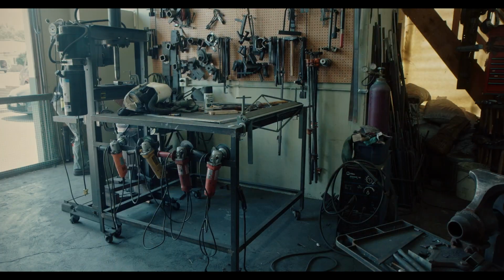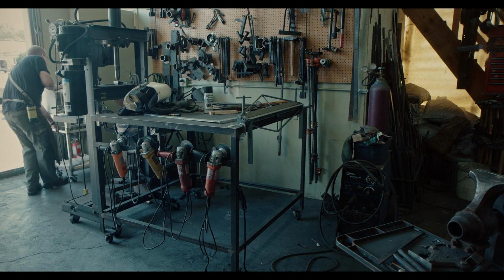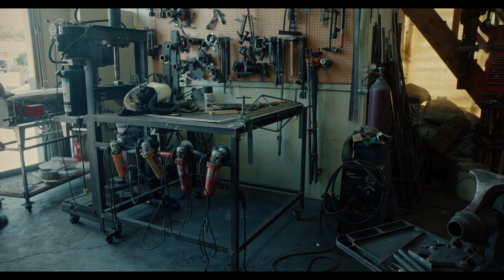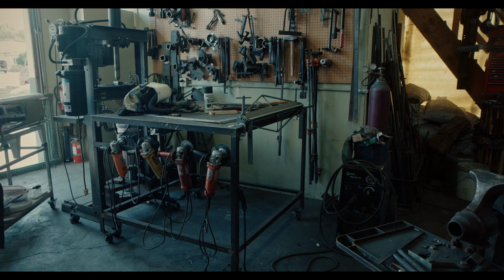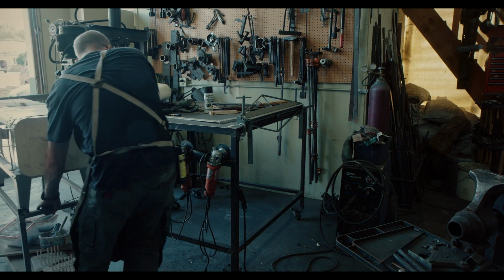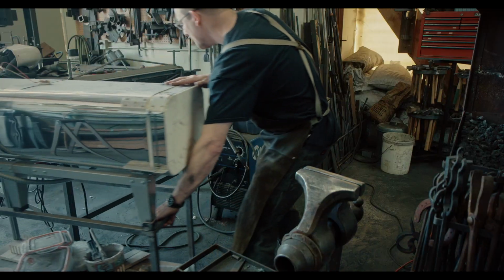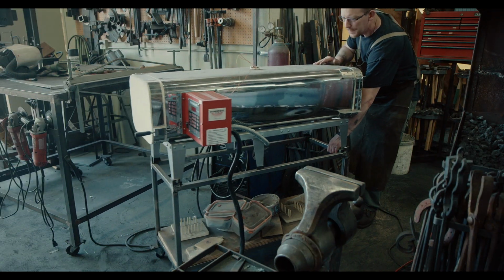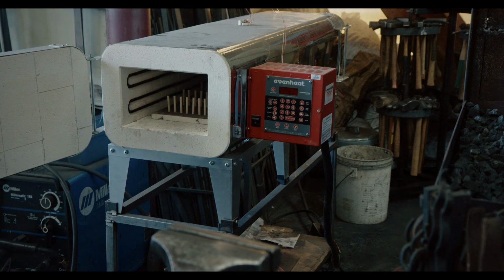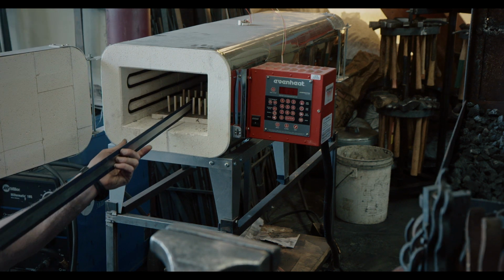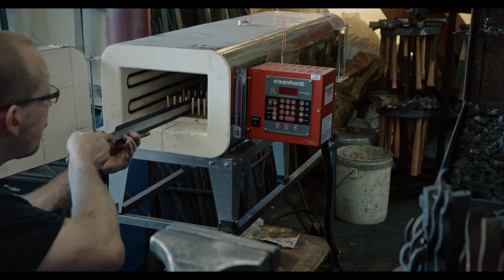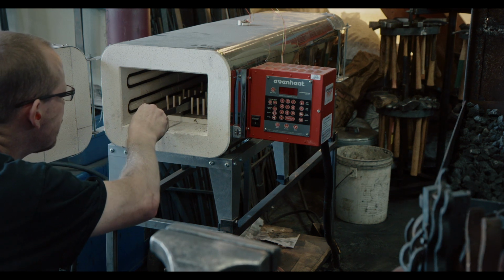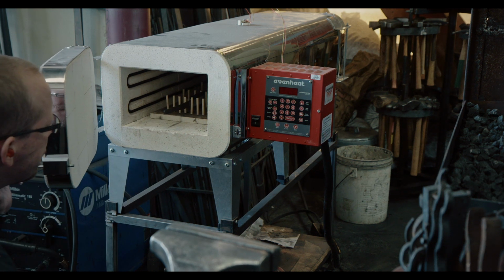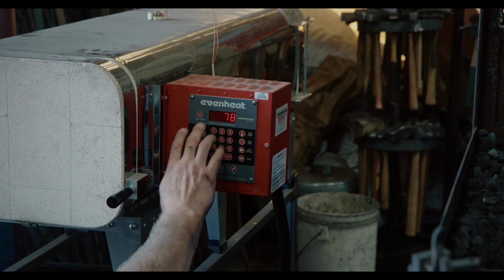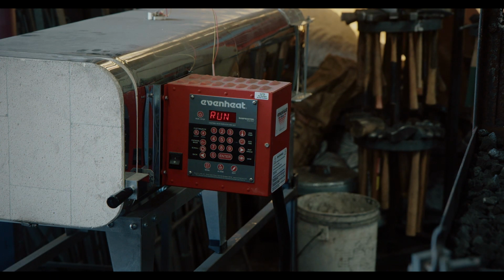Normalizing is the process where the sword is heated up to critical temperature and then allowed to slowly cool down. This relieves stresses in the blade and also reduces the grain size. Since metal has a crystal structure, it can form grains in which the structure aligns and creates macroscopic grains. These are brittle and can lead to fractures around grain boundaries. Before heat treating, it usually is a good practice to reduce the size of these grains. That's what I'm doing now. I'll heat the sword up to its critical temperature and then let it cool in the air.